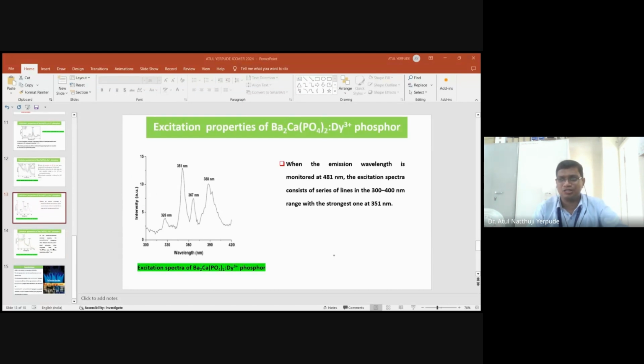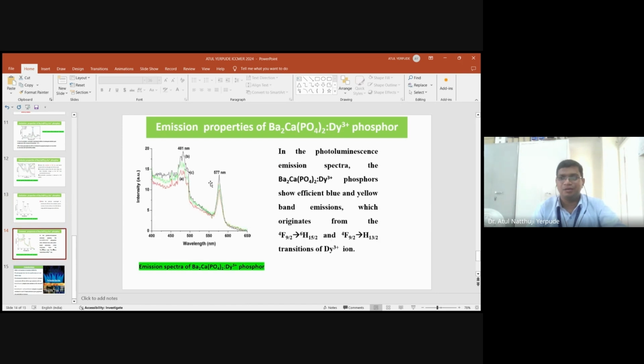This excitation spectra shows a maximum excitation intensity observed at 351 nanometer. So we take this excitation peak for obtaining the emission spectra, and this one is the emission of the Dy3+ doped phosphor.